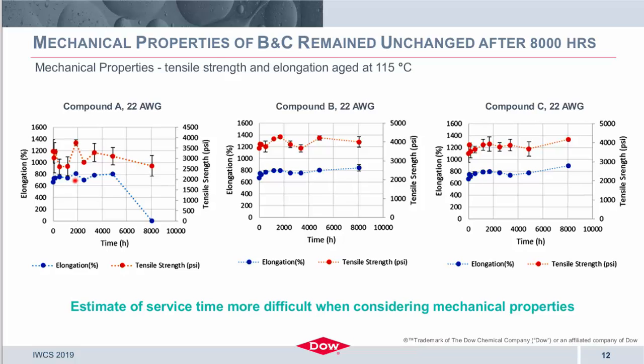And really what is important to point out is you see the difference between compound A versus compound B and C, where compound A begins to fall off around the 4,000 to 5,000 hour aging time as far as elongation. However, compound B, compound C, as I mentioned, continue out to 8,000 hours and remain relatively unchanged, with no decrease in its properties.